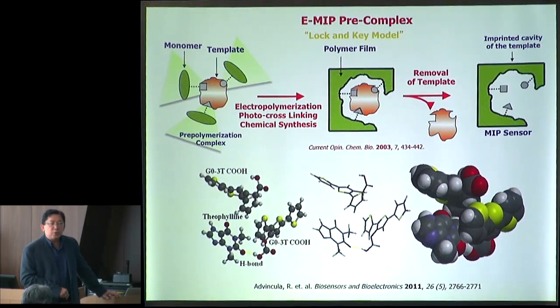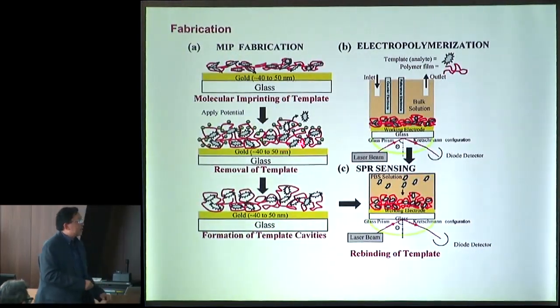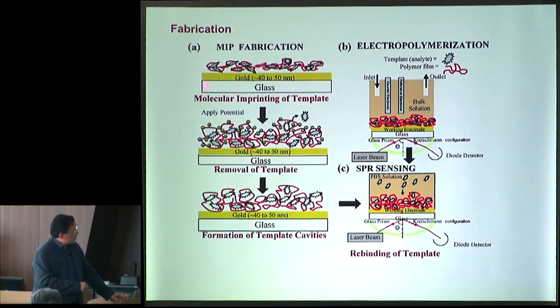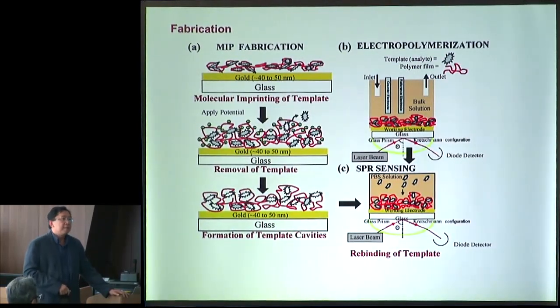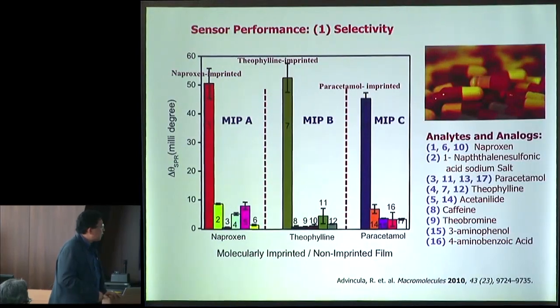with the number of monomer pairs that will lead to higher binding constant. And we do this by ab initio, semi-empirical calculations, or simply MM2 calculation. That shows that for theophylline, for example, we have optimum complexation with 1:2 ratio. Okay? 2 monomers to 1 molecule. So this was done essentially by electropolymerizing this on a gold working electrode. This gold working electrode builds a film that constitutes the template plus the polymer, and then we can remove the template and form cavities on that film. Once we do that, we can use SPR to detect back and forth, or to distinguish the template from other analytes by sensor studies.